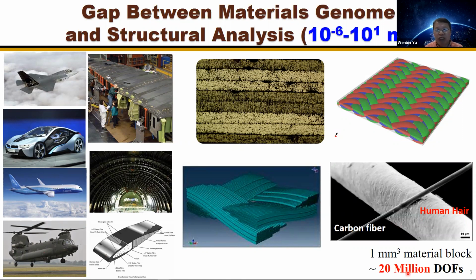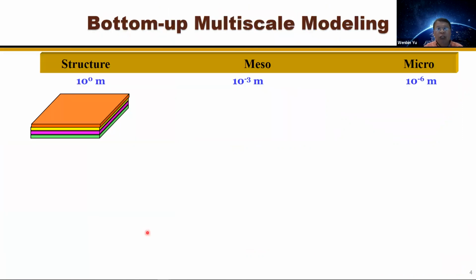The reason being that if you're familiar with finite elements, it's even harder to cross two length scales. For example, for a 1 millimeter material block, if we want to capture fiber details, your element size cannot be more than the fiber. Then you're talking about millions of degrees of freedom. But here we need to cross 10 length scales from micron to meters. And we also know that structure behavior is directly affected by how we engineer the fibers. So we need to find an effective way to bridge the gap between the materials genome and the structure analysis. Let me use an example.